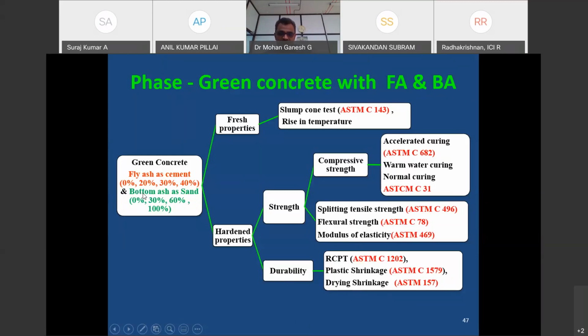Since the bottom ash is a coarser material, we have to do proper dosage, proper mixing, and proper care. If you are not doing it, it will give a reverse effect or anti-effect. In that way, the plastic shrinkage will be very high, as well as drying shrinkage also will be very high. So we have to be very careful while using the bottom ash, and with super plasticizer and all. So this is a must one. We have done all, and it was compared with ASTM standard.